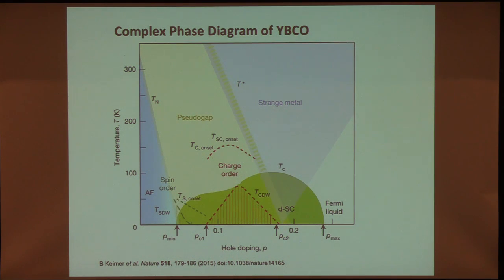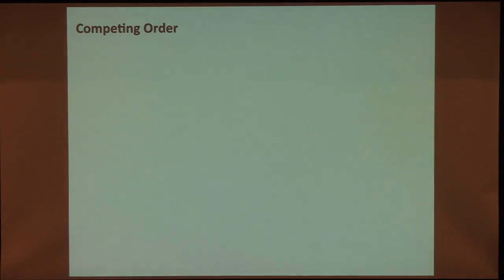So here's again another image of the phase diagram of the cuprates. And one of the things that appears, this is in this consensus paper, and the fact that it appears in this consensus paper is important. What's occurred is that the occurrence of charge density wave order in this regime is now not a speculation, and it's not controversial. It's really been established. And let me look at a little bit of that just to illustrate the point.